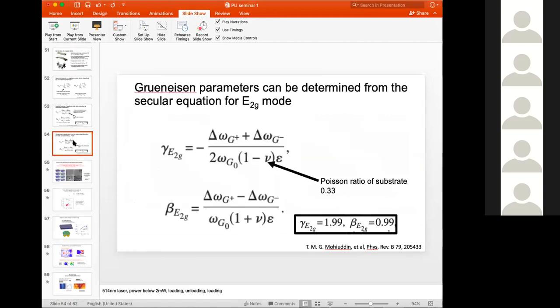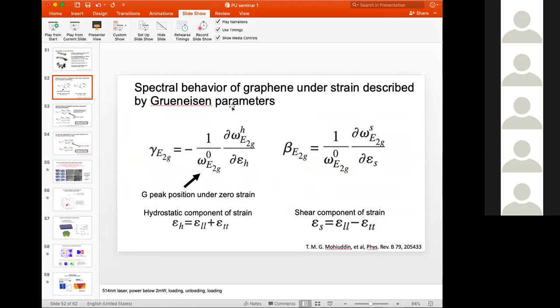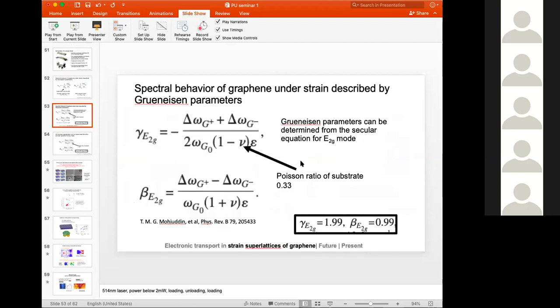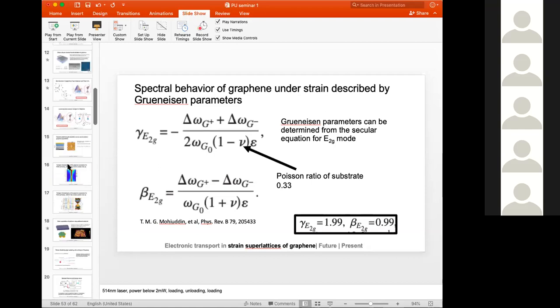So this is the definition of Grüneisen parameters. These are how they're defined. You have the shear strain and the hydrostatic strain components, and you essentially estimate these parameters. For graphene, it is possible to estimate these parameters from a secular equation of the E2g mode. And usually the experimental estimates give Grüneisen parameters to be like 1.99, 0.99. So I'm not very sure about the details of the theory of this, but I'm sure there is one. Okay. Thank you.